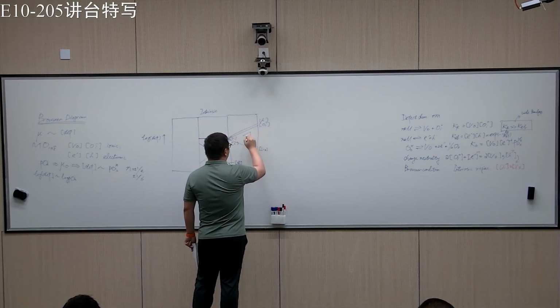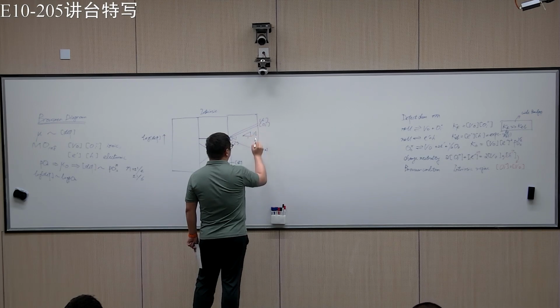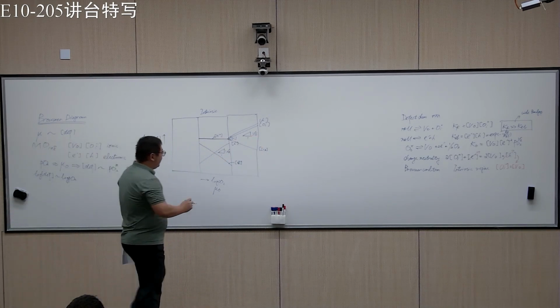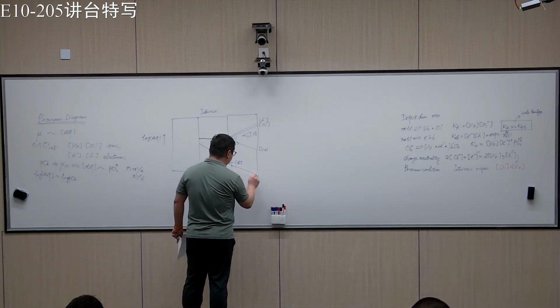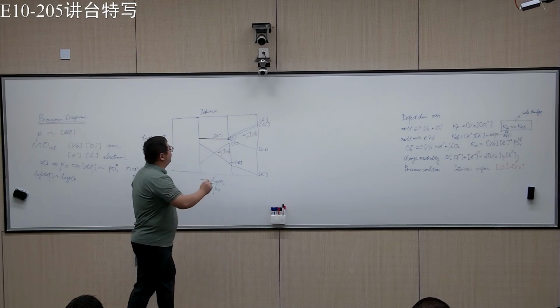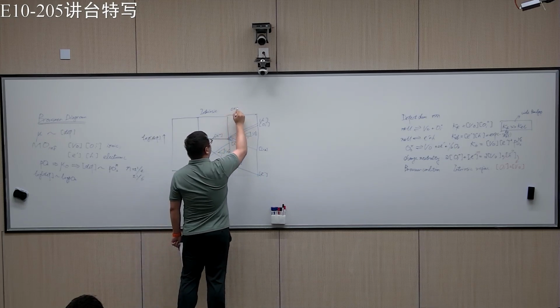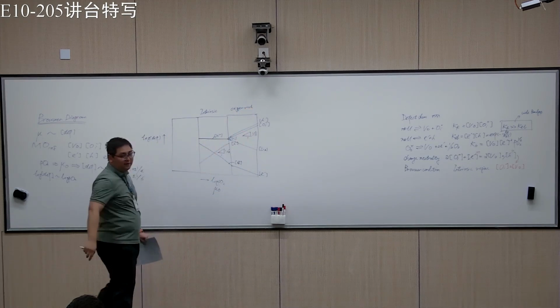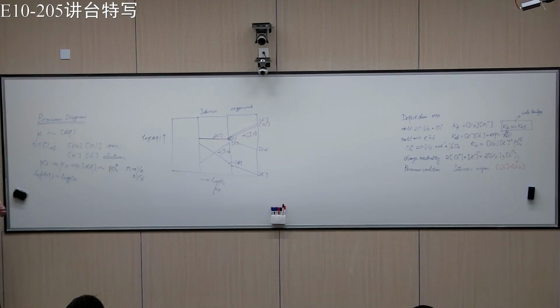We solve for the defect chemical equilibrium, and the slope is 1/6. Okay. So the same thing as the electron here. So this is the electron. So this regime is called oxygen-rich because we are increasing the amount of oxygen in this case.